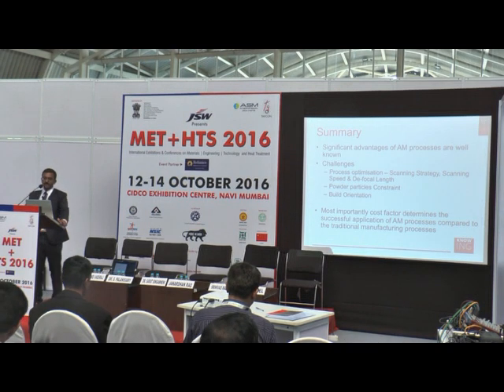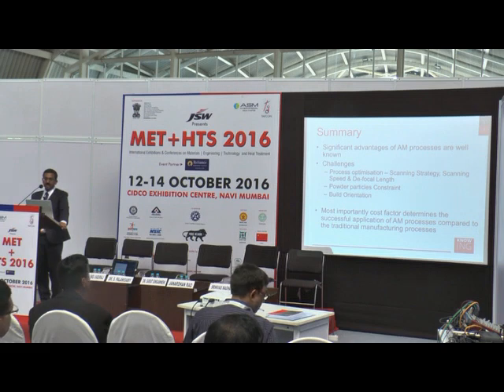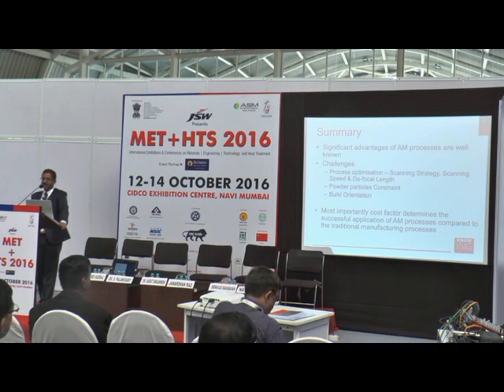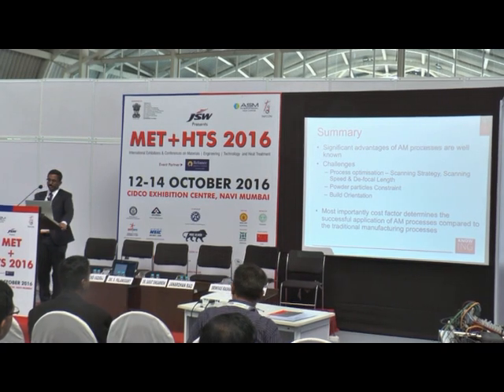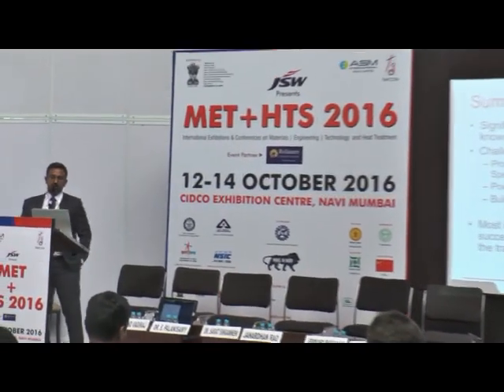So finally, to summarize, obviously there are significant advantages for additive manufacturing. There is no question about that. But the challenges I mentioned are key things: process optimization, especially looking at the scanning speed, scanning strategy, and also the defocal length, which are the critical parameters to look at. And also powder particle size. Still, the manufacturers and suppliers of the powders can say you can reuse it a number of times, but there are certain limitations there. So you have to find your own constraints within the powder recycling process. You have to identify how long you can use the powder depending on the parameters you are using. So that's the other challenge you have to identify yourself.